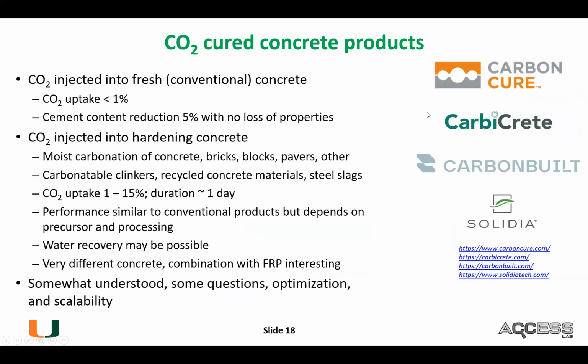There's also CO2 cured concrete products. One way of doing this is just to take your normal fresh concrete and then inject a blast of CO2 into it. The uptake in this case is really pretty low, maybe 1%, maybe even less. And the claim from the startups has been that you can actually reduce your cement content by about 5% because of the formation of nano calcium carbonate phases, without actually reducing the concrete performance.